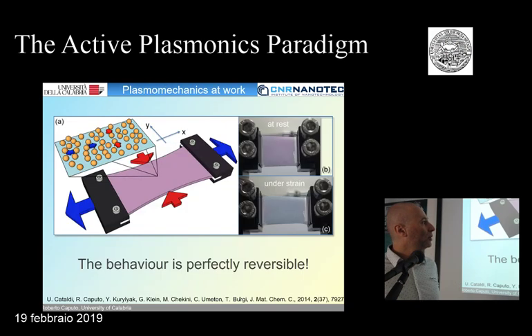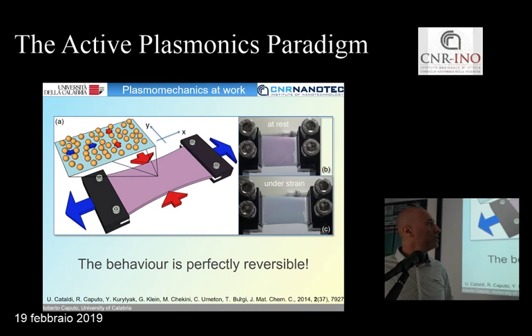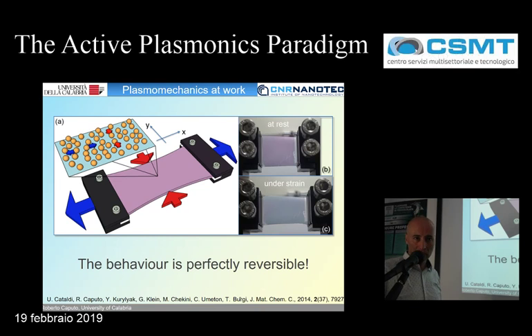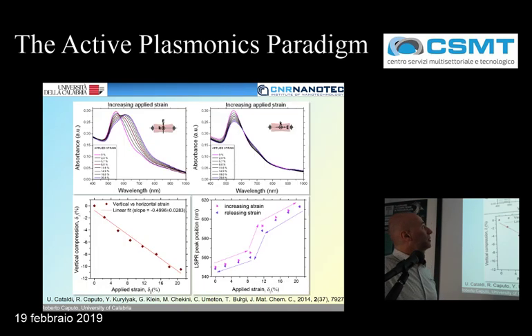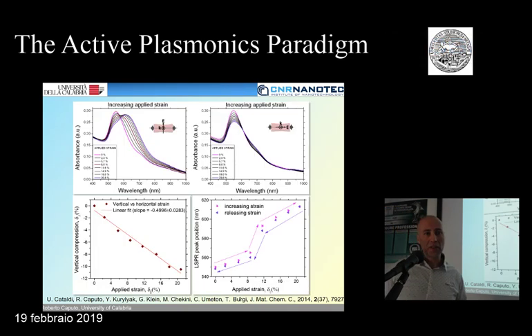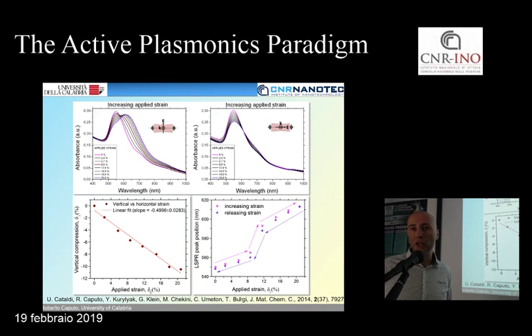So when we go to the real experiment, this is what we obtain at rest. The sample shows one color. When you stretch it, the color is different. So by elongating the sample, you change its color. And the experiment is quite simple and reversible. And here there are more quantitative results. You can see that you have a very nice shift of the resonance, which corresponds to the real change of color.